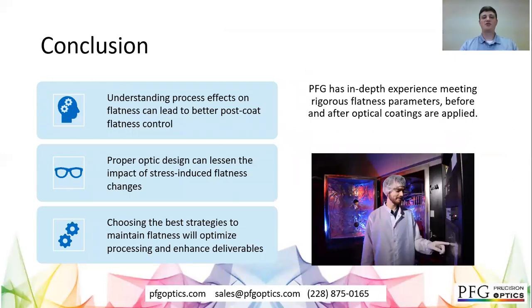So in conclusion, understanding the effects of coating processes on post-coat flatness for high aspect ratio parts is necessary to achieve these tight tolerances on these parts. Optical engineers can use this information to better understand what's required to produce the parts that they're designing. In addition, the proper optical design, for example, the lowest aspect ratio possible, can lessen the impact of the stress-induced flatness changes in coating. So PFG has in-depth experience using these strategies, and we optimize our processes with the best strategies in order to produce these tight tolerance, high aspect ratio coated optics.